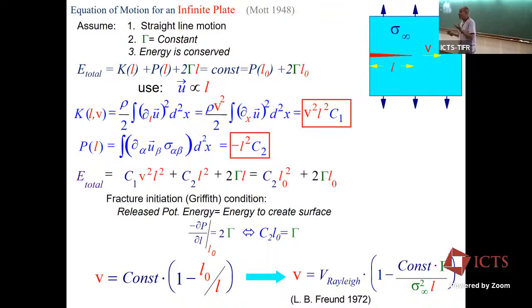Now, why does it have to be the Rayleigh wave speed intuitively? Because suppose the fracture energy went to zero. Do it like a turbulence argument, if you like. So if we look at this expression, for example, the fracture energy going to zero is equivalent to infinite stress here. Now, if the fracture energy is zero, it means that the crack is actually moving as a disturbance and it's not dissipating any energy. That's exactly what this is doing. It's a wave moving along a free surface, and that moves at the Rayleigh wave speed, and that's also the fastest that a crack can move.